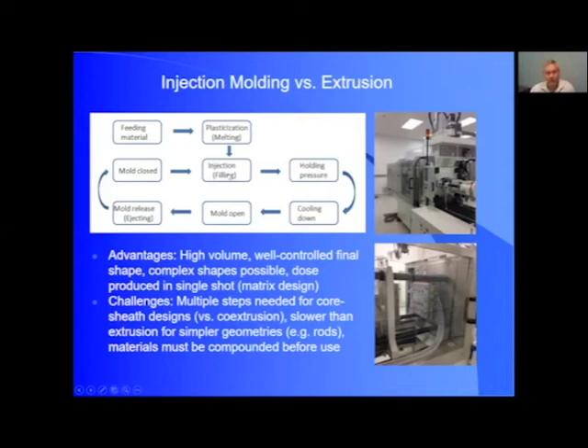And so with injection molding, then you're filling a cavity, holding it at pressure, allowing it to cool, opening the mold, releasing it, and basically continuing the cycle. That's one thing to point out, this is an example for thermoplastics. Typically silicones work in the opposite way. You have a 2-part system that you're injecting cold into a hot mold, and you're having a reaction to cross-link the silicone within the mold and then ejecting it that way. So silicones and thermoplastics behave kind of in the opposite manner in terms of how they set.